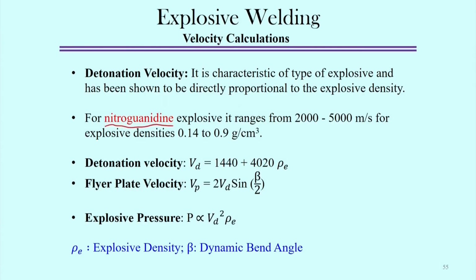In this case, the velocity actually ranges from 2000 to 5000 meters per second, and the density is around 0.14 to 0.9 gram per centimeter cube. So, using this specific explosive, the detonation velocity can be empirically related as 1440 plus 4020 times rho e. That means the detonation velocity depends linearly on the density of the explosive.